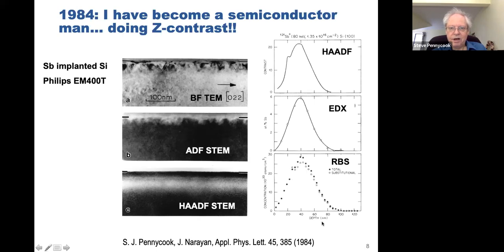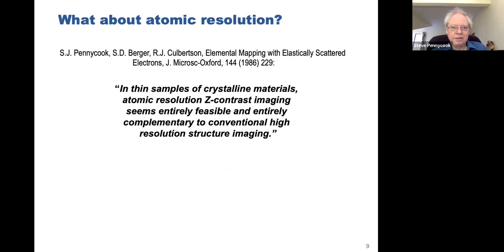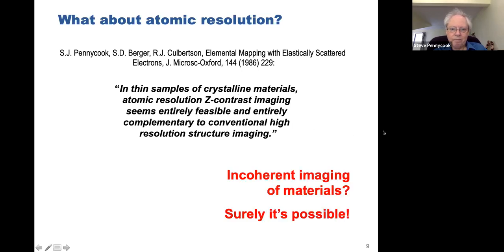So this was really the start of the Z contrast and what put the seed of atomic resolution into my head. And I thought, well, it's incoherently generated. It means you get scattering when you hit the atom, and if you're not on the atom, you don't get scattering. It should be an incoherent, directly interpretable image. So I published that idea in 1986. Should be entirely complementary to conventional high resolution structure imaging. Surely it had to be possible.